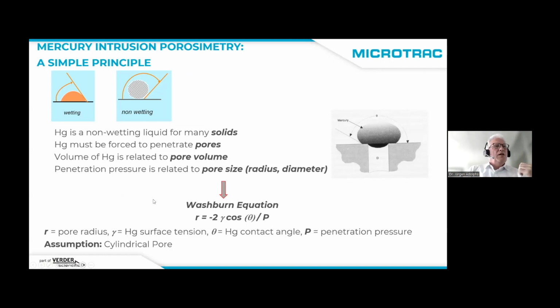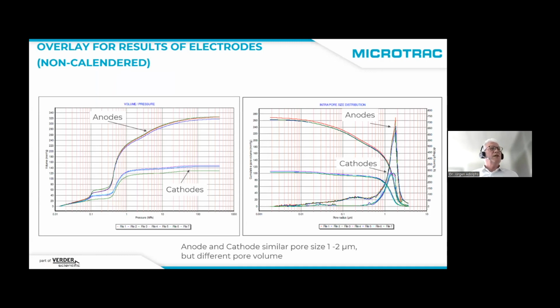And one example here for an electrode, anodes and cathodes. These were non-calendared, for example. We see here the anode measurement with a much higher pore volume, in the range of about 320 cubic millimeters per gram, while the cathode was in the range of about 140. When we look at the ratio of the intruded volume over the pore radius, so the dV log over the dr, which is shown here in these peaks, we see that the pore size for both is quite similar, in the range of 1 to 2 micrometers. So the pore size is very similar, but the pore volume is different.